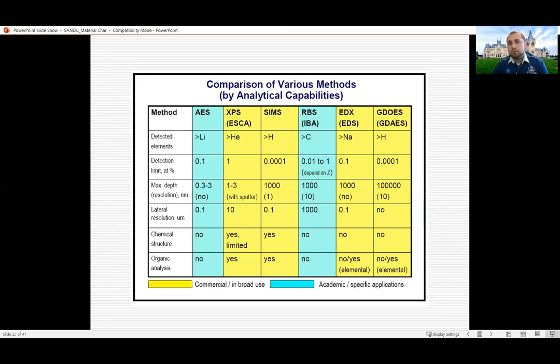Now here we have a comparison of various analytical methods according to their capabilities. The techniques, we have the element that they can identify. So lithium can be, all elements above lithium can be identified by AES. Again, as you can see, XPS is going lower to helium, SIMS even starting from hydrogen, RBS only from carbon, EDX from sodium and higher, but now there exists EDX with better results. Also GDOES starting from hydrogen, you can see the limit starts at 0.1%